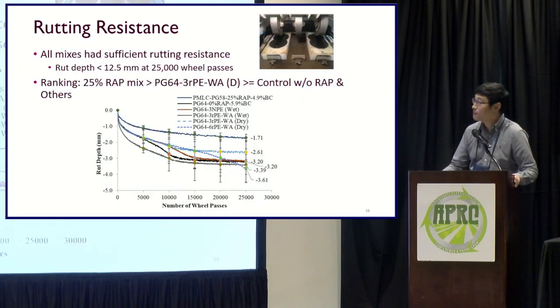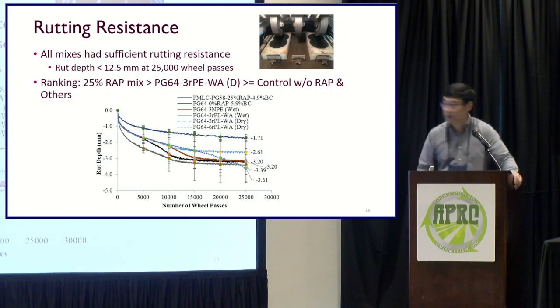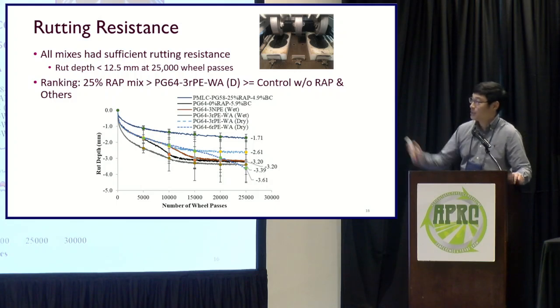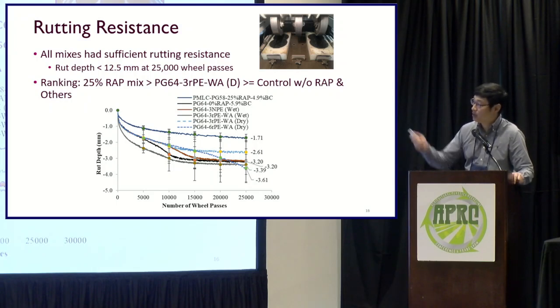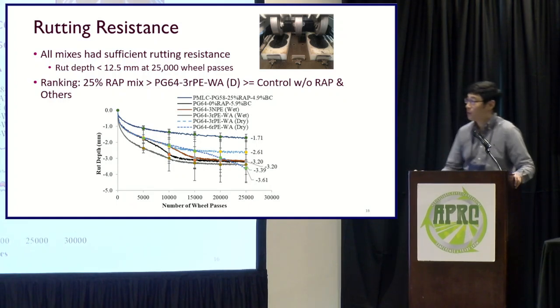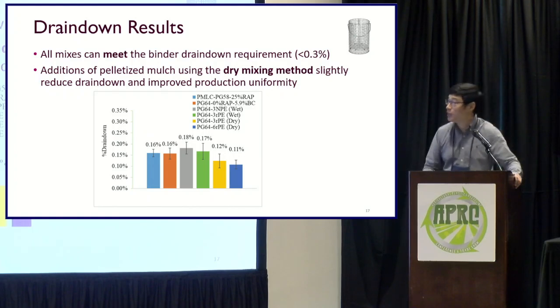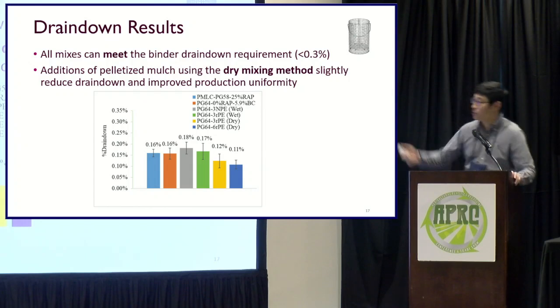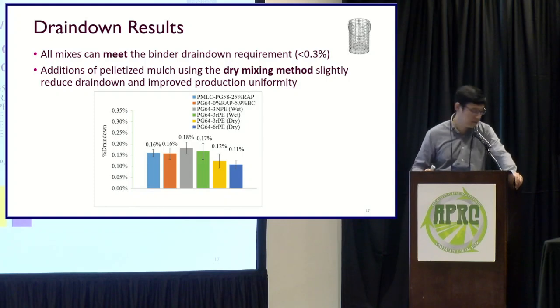Well, the rutting resistance, there's no issue for all mixes. The rut depth is much less than the 12.5 millimeter at 25,000 wheel passes. Well, for the RAP, definitely the 25% RAP mix has a lower rut depth, followed by the 3% RPE from Washington using the dry mixing method. But in general, there's no rutting issue when we add the plastic into the mix. And for the drain down test, again, when we add the pellet mulch using the dry mixing method, it reduces the drain down, and actually that improved the production uniformity.